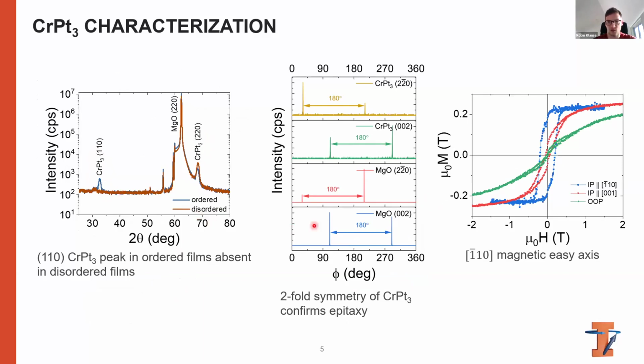Then we did in-plane X-ray diffraction measurements to confirm that the films are epitaxial, and we see the twofold symmetry of the chromium-platinum-3 and the well-aligned peaks with the substrate, which confirms that we have epitaxial films.